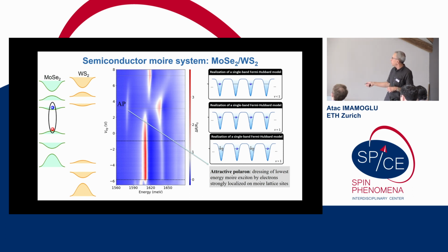What we can do is tune the filling factor and see what happens. What you can see already here, which I will come back to, is that the oscillator strength picks up, goes to maximum at nu equals 1, and then disappears as we approach nu equals 2. Nu equals 2 means full filling with both spins of the lowest moire band.